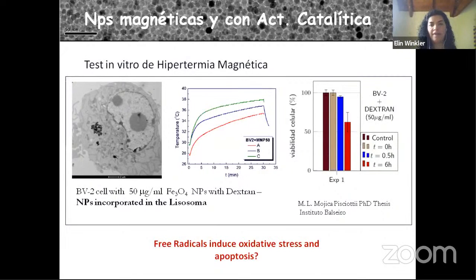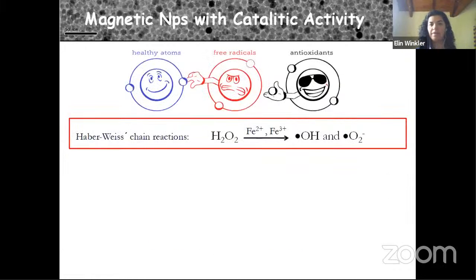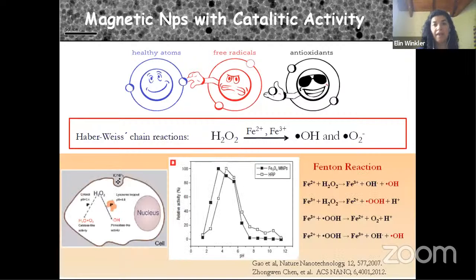Well, and here we arrive at the question of whether free radicals are induced during the hyperthermia, and that is the reason why the cells die. Free radicals are very reactive molecules that have unpaired electrons, and in that way oxidize the molecules in the medium. In the cells, we have peroxide that decomposes into free radicals, a very slow reaction, and it is known that iron produces a catalytic generation of these free radicals. And a very recent work found that the nanoparticles produce these free radicals.